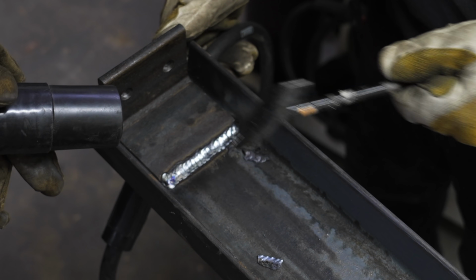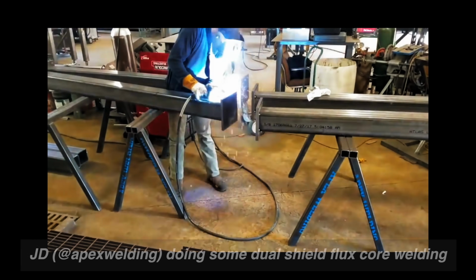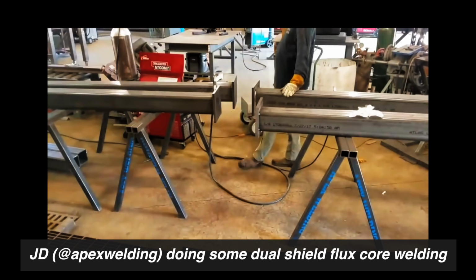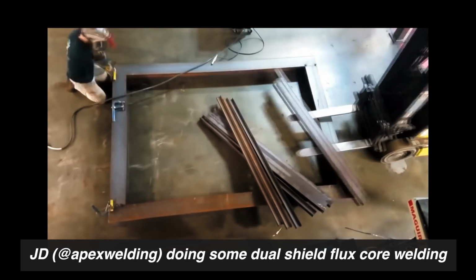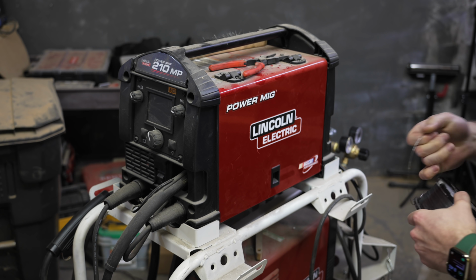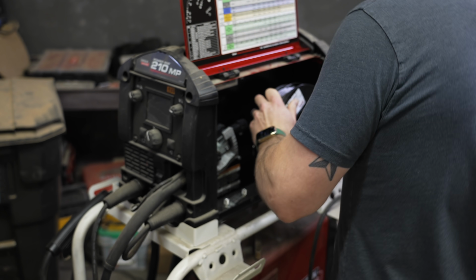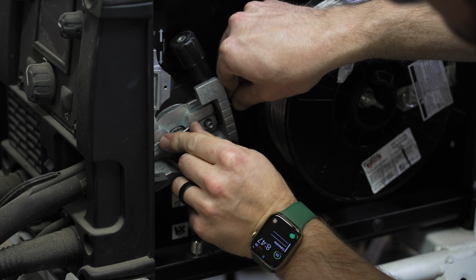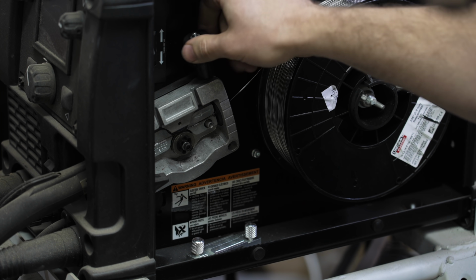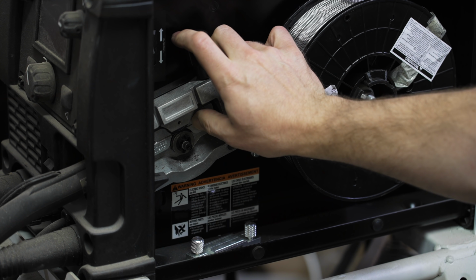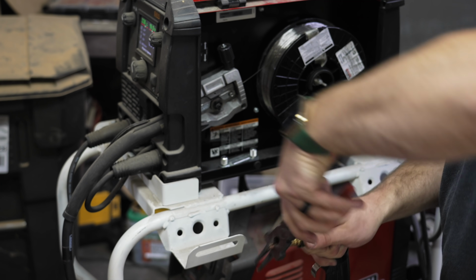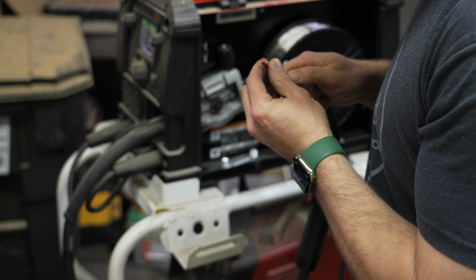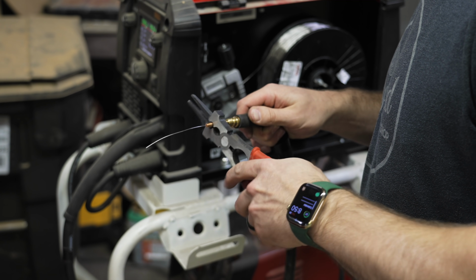My buddy JD from Apex Welding is a big fan of dual shield for this type of structural work, and he gave me a bunch of tips on working with dual shield, so big shout out to him. So to switch from solid core MIG, which is what I usually use, to dual shield, I first removed the solid core wire off camera, installed a knurled drive roll, and then fed in the new wire. And I also changed the contact tip on my torch to match the 0.035 diameter of the dual shield wire.